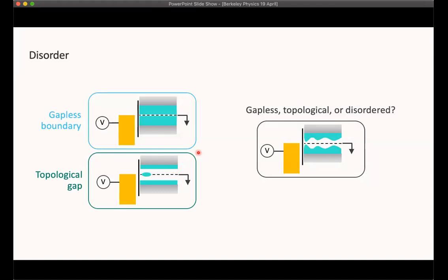So here's the problem. All of these cartoons are well and good because they behave very well because I made them behave very well. But when we're measuring something that we think is a gap that is closed, like at the gapless boundary of our phase transition, or we're measuring something that we hope is a Majorana, but is in fact some blip in our spectroscopy at zero, how can we be sure that these are the states we expect and not just some local disorder in our density of states near this tunnel junction that is clouding our view of the entire bulk of our wire?